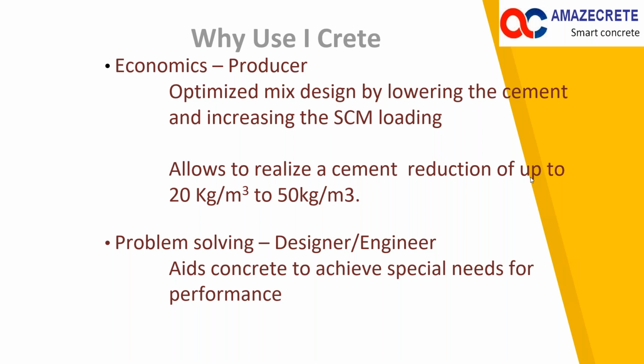For example, you have a mass foundation or a thick foundation with a high grade concrete. So you cannot use more OPC because heat buildup takes place and then you have thermal cracks, etc. In such situations, you can reduce the OPC content and increase the SCM content using iCrete, and hence it solves the problem of the designer.